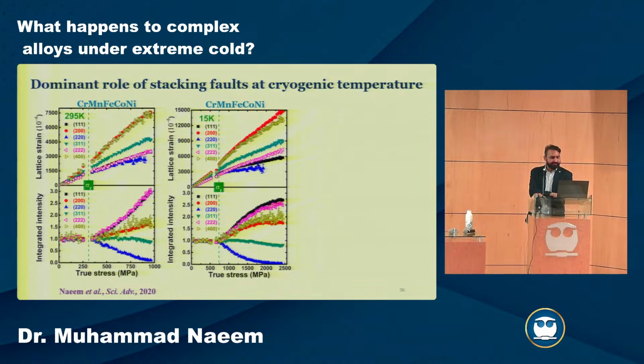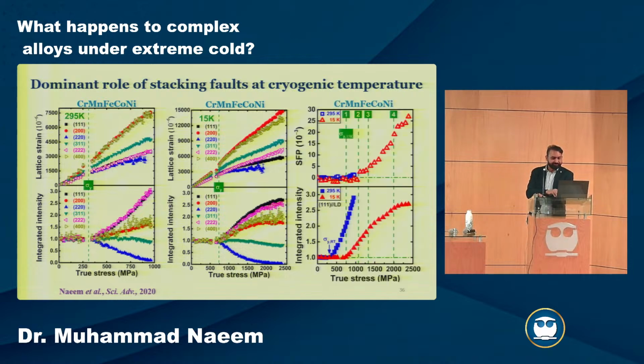Here you see this pink and the black were overlapping. Actually, you cannot see the black at all. But here you can see there is separation between these two. Similarly, this red and this green, and again you see separation at high stress. There is also a change in how the texture evolved. Initially it is increasing, as it was over here, but at the end it almost saturates.